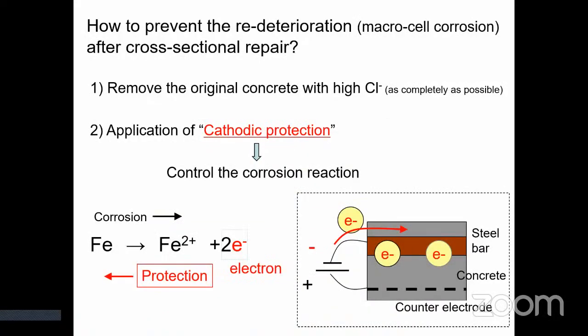Here, I'll explain how to prevent re-deterioration after cross-sectional repair. First, remove the original concrete with high chloride ion. Second, apply cathodic protection. This method is often applied to steel structures, such as steel pipe piles. This method can control the corrosion reaction by applying electric power.